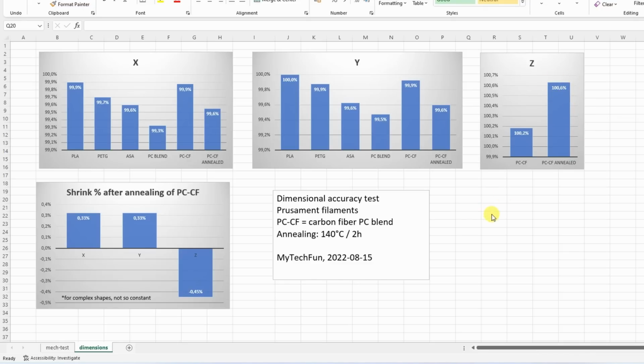Now, what is this shrinking in percentage? Well, in X and Y direction, it is very similar, approximately 0.3-0.4%. And in Z direction, it is a negative value. This means it extends, between 0.4 and 0.5%. Keep in mind, for complex shapes, this is not so constant, so you cannot just compensate this percentage in design to get accurate printing dimensions.